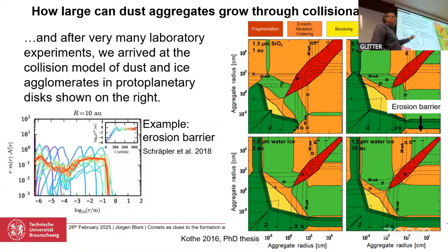And in this work, and this is why I show this plot here, in 2018, we painted the whole thing green, except for this corner. So we allowed every collision to lead to sticking, except for this little erosion thing. And you're seeing here, this is mass, this is size, this is a frequency of occurrence. We start at early times, and the time evolves, so we're growing and growing and growing, and then suddenly we stop. And the maximum size we can reach is 10 centimeters. So even in the case that you ignore all the fragmentation events, I'll show you a video later, all the bouncing, ignore all the physics, and only allow the erosion, the maximum size we could grow in the protoplanetary disk is on the order of 10 centimeters. Unfortunately, nothing better is possible.